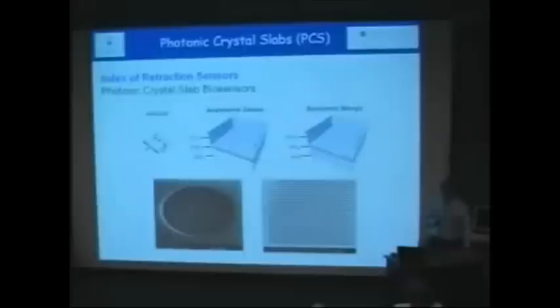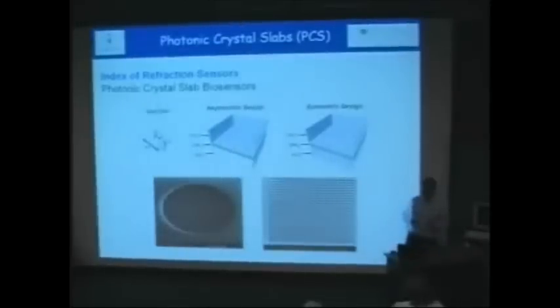So we went ahead and fabricated some of these designs after we modeled them. And we have looked into two cases. In both cases, we have a periodicity of photonic crystals. So this one was using E-beam lithography. In the past, we also used optical lithography to create 2-dimensional arrays of holes. And the diameters of the holes could be anywhere between 200 nanometers to a micron, depending on your design. And the periodicity is between half a micron to a micron. So this is how it looks in an SEM, and this is how the whole structure looks in about 200 micron or 500 micron diameter. So that gives you a feeling for the structure that we make, and you could even see the moire effect, because even the SEM had some effects when we tried to measure it.